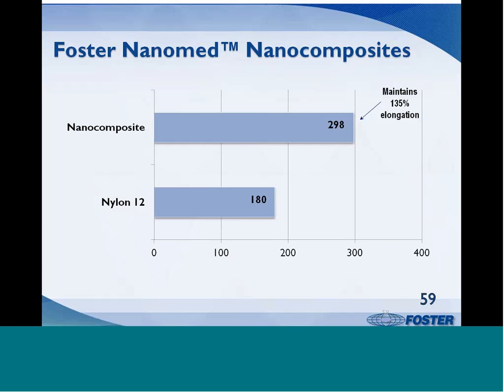One of Foster's discoveries was that nanoclay in polyamide elastomers maintains or surpasses the ductility of the base resin. This was very surprising given the reputation of polyolefin nanocomposites. With many polypropylene homopolymer nanocomposites, ductility drops faster than the other properties increase. This leads to Band-Aid formulations that never achieve the originally desired result. This was not the case with elastomeric polyamides.